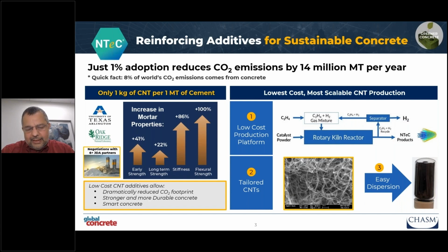Why? One is cost, as some of my earlier colleagues spoke as well. Cost is critical, dispersion is critical, and scale is critical. And to cater to all these three, some of you might wonder what are nanotubes. My previous presenter spoke about graphene. If you fold it into a cylinder form, it's a tube that's called a single-wall nanotube. If you have a Russian doll-like model with multiple tubes, that's a multi-wall nanotube, as you see on the extreme right. The diameters we are talking about in concrete are around 10 to 15 nanometers, and length as made maybe around 5 to 10 microns, but as you disperse, it would be much shorter.